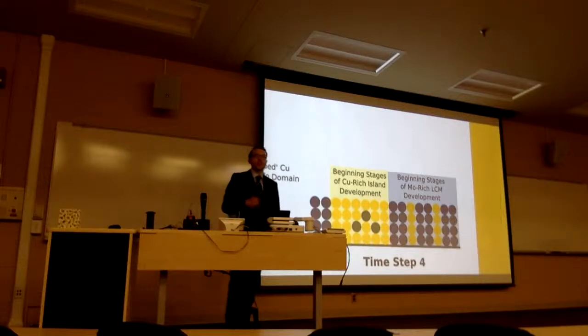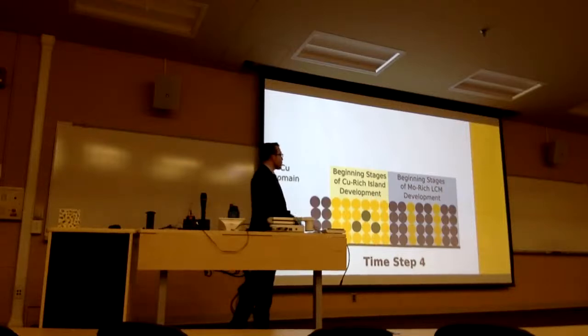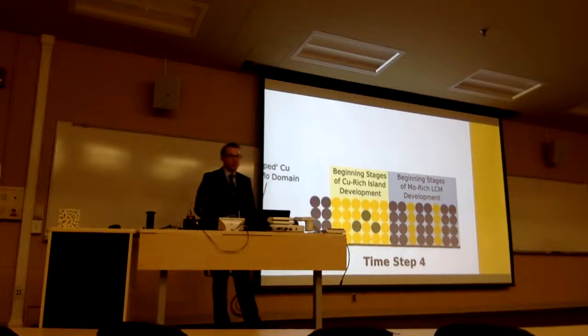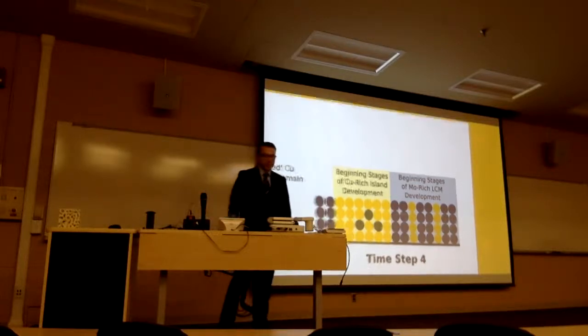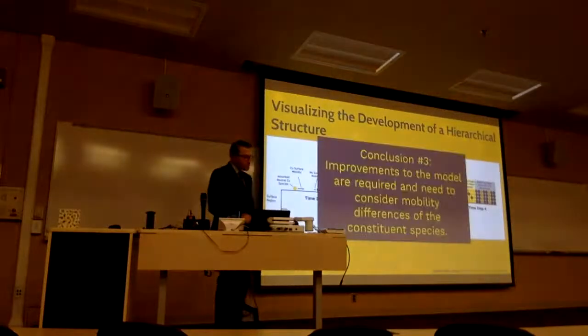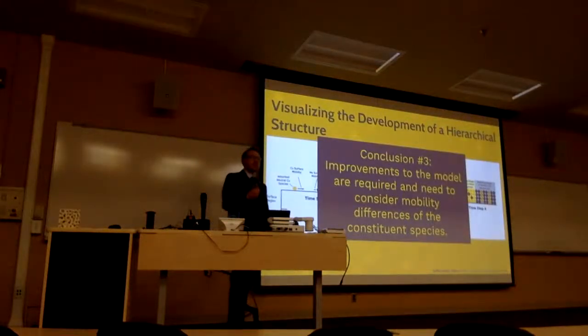What you can start to see is the development of a disparity in the phase fraction depending on the location inside the sample. In one, we have a disparity in the amount of copper versus moly. In the other, we develop these copper islands, where the phase fraction of the material we predict is much closer. We can see the development of a homogeneous morphology, or an LCM morphology, that we saw at higher deposition rate. So what we can conclude here is that, in the very least, we need to improve the models that we described before. We think we need to consider the mobility differences between the constituents during deposition.